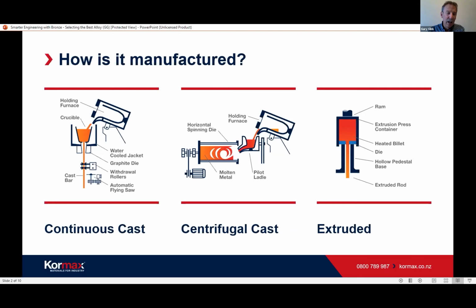And the plant we have in New Zealand, in Christchurch, is capable of doing up to 200 millimetre in diameter, but very shortly, in fact, probably this week, there'll be some new plant commissioned that will do up to 300 millimetres. And the tubes can be made with wall thicknesses down to about 6 millimetre when you're down in the 25 to 40 millimetre diameter. Once the diameter gets bigger, the wall thickness has to increase. And at the 200 millimetre size, you'd be looking at around 20, 25 millimetre wall thickness.